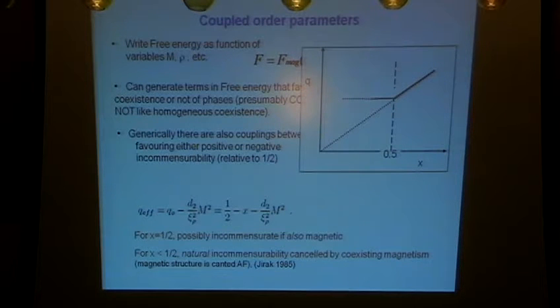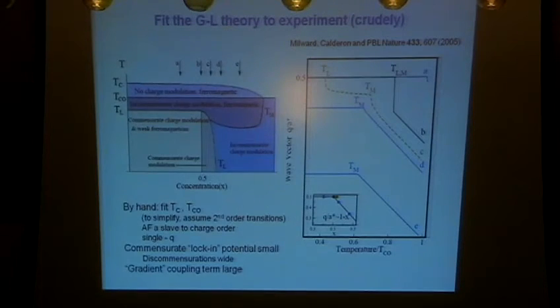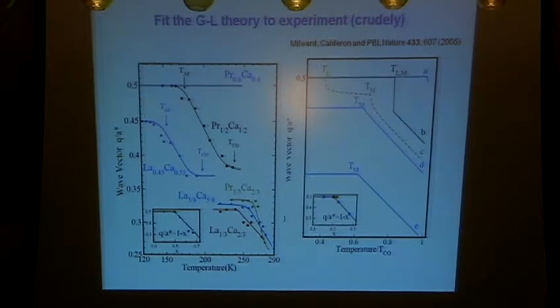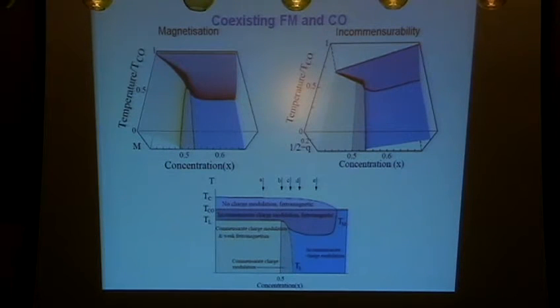Now there's no theory going here. I mean, there's no numbers or anything like that. So you should try and fit to experiment crudely, and with a reasonable sense of parameters you will get things that look like the data. I can go through that in more detail. One doesn't have to tune very much. But you get a very complicated structure of phases. You get phases which are, you know, here's magnetization, here's the incommensurability. You can have things which are ferromagnetic and incommensurate, ferromagnetic and commensurate, commensurate and non-ferromagnetic, and whatever. And a lot of stuff which automatically happens.